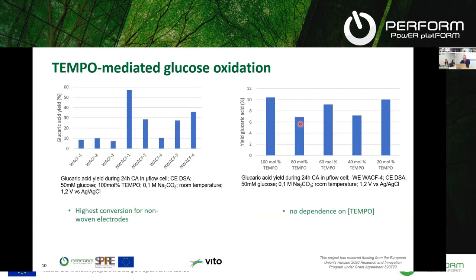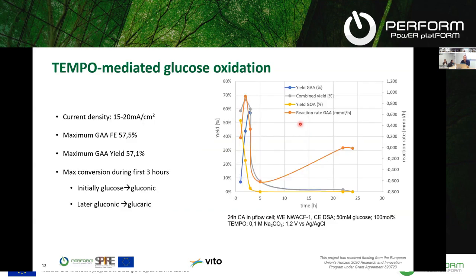One of the conclusions of this screening was that we get the highest conversion to glucaric acid with some non-woven electrodes, which we selected then for further testing. And we found also little to no dependence on the tempo concentration, ranging from 20 to 100 mole percent tempo. 100 mole percent, of course, being the same concentration as the initial glucose concentration.